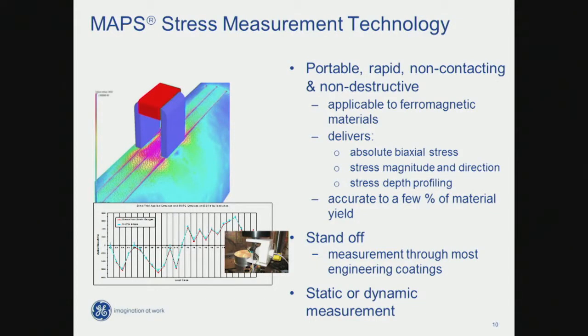epoxy coatings, or whatever. You can think of it as a highly quantified, low-frequency eddy current technique in terms of its physics, a kilohertz or so. That allows us to do static measurements clearly, but also we can do measurements at some speed. So that's the sort of technology. It's magnetic. We actually measure the magnetic characteristics, the permeability, of the material, and underneath the hood is the physics to be able to relate changes in those magnetic properties to the stress that we as engineers understand in terms of megapascals.